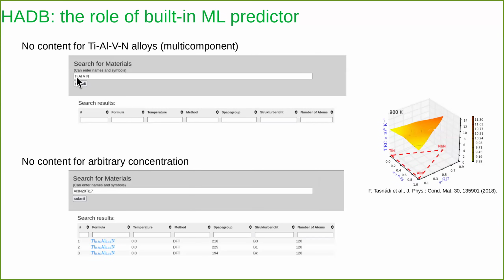You see, I typed in titanium aluminum vanadium nitride, and nothing is happening there. Or what happens if you are looking for a particular concentration which is not stored? Of course, we cannot generate SQSs for arbitrary concentration, so here I just emphasize that you have only particular ones. But when you, for example, would like to know the thermal expansion of an alloy you want to engineer, you would like to see a set of continuous maps. That is the point where the machine predictor is serving us.